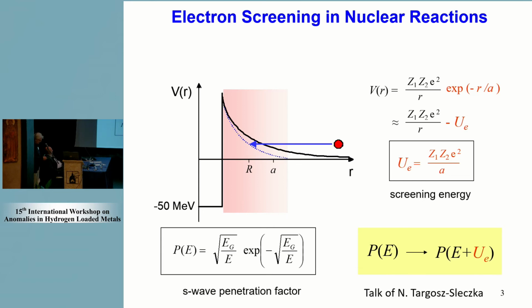So very briefly, here we have a Coulomb barrier we should tunnel, and then you have here the Coulomb potential, and here a screening function. We can describe it by a screening energy with the screening length that reduces the height of the Coulomb barrier, and then the penetration factor that describes this tunneling effect can be described very easily. If you have the screening energy, we put an additional term in the energy, and then we can describe this tunneling effect in the presence of surrounding electrons in some materials, mostly metallic materials.